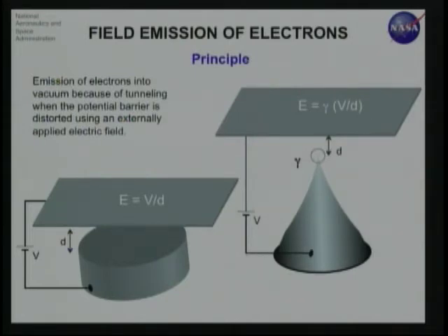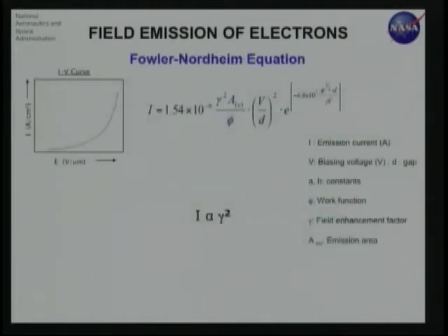So, for example, if you make the object fairly sharp, the radius of curvature introduces a field enhancement locally at that tip. The applied field, which is voltage divided by the gap between anode and cathode, gets amplified by a factor called the field enhancement factor, gamma. If you can make gamma on the order of several thousand, then by applying just 1 or 2 volts, you'll be able to generate a lot of electrons. That's the principle, that's the idea.